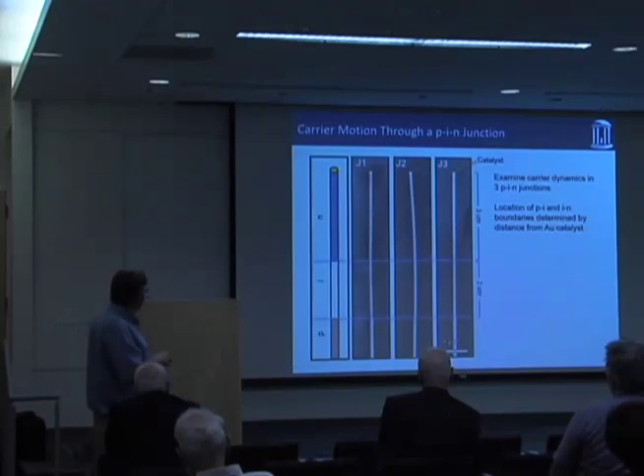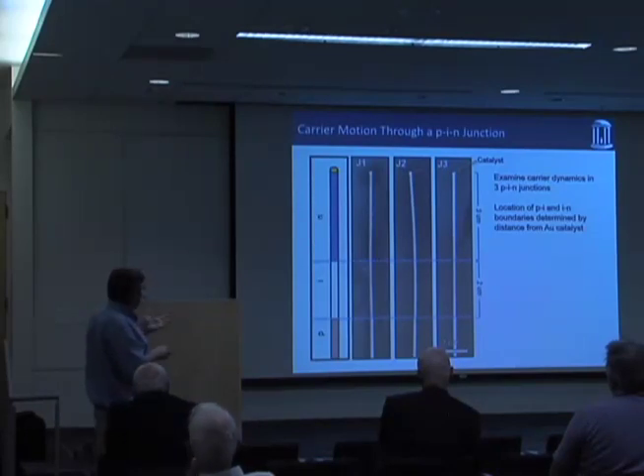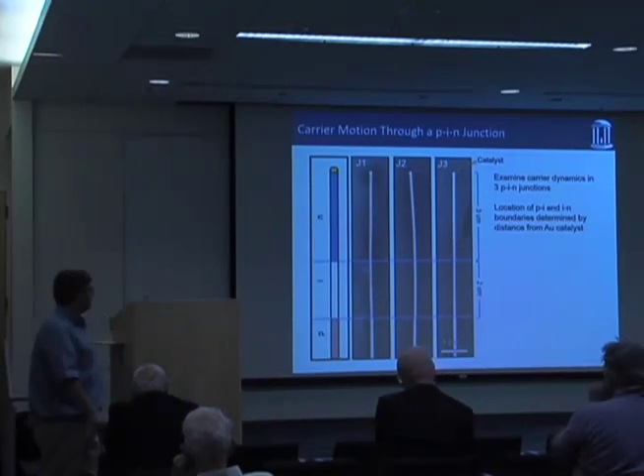These are the junctions themselves. We looked at a bunch of them, or we looked at like 5 or 6 of them. Here are 3 different ones. At the end of the wire is the gold catalyst, and then we know based on how they grew them that there's like 3 microns of an N-type material, then 2 microns of an undoped material, and then there's a long section of P-type material.